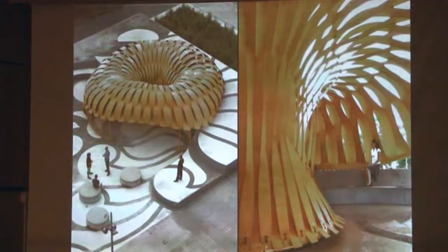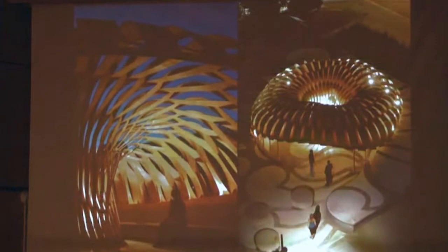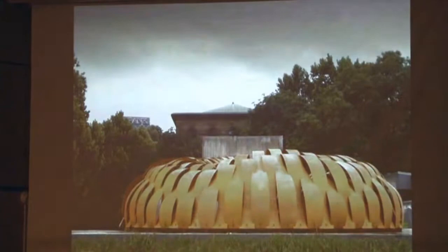Because the combination of the pre-stress that results from the elastic bending and the morphological differentiation of the joint locations allows using only extremely thin plywood. In fact, the entire structure, which had a diameter of more than 12 meters, could be constructed by only using birch plywood with a thickness of 6 millimeters. So there is no building part thicker than 6 millimeters.